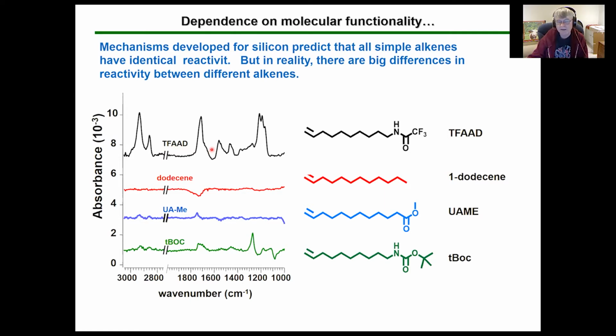And if we look at the ability to graft other molecules, which we can probe, now probing carbon on carbon is hard. You can't use XPS very easily to quantify a molecular layer on diamond. So oftentimes we rely on infrared spectroscopy. Now infrared's pretty insensitive, but these absorbances are on the order of 10 to the minus 3, so maybe 10 to the minus 4 absorbance units for most molecular layers. But with a lot of attention, that's very doable.